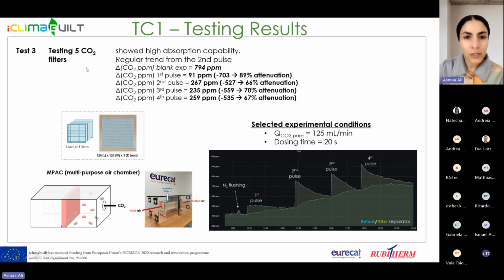Coming to the carbon dioxide filter testing, in this test we used only 5 filters, but in the final test case we will have 25 filters. As shown here, we have performed many pulses. The pulse duration is 20 seconds, and these 5 filters were tested in a multi-purpose air chamber where carbon dioxide dosing is introduced on one side, and the evolution of this concentration is recorded on the other side. From this figure, you see a regular trend from the second pulse, with an average of 67% attenuation, and this is only for 5 filters.